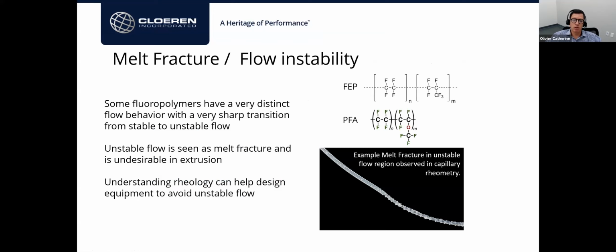For example, we designed a lot of dies for fluoropolymer applications. So here are some examples of fluoropolymers like FEP and PFA. So highly fluorinated molecular structures and very specific flow behavior. These materials tend to very quickly become unstable in the flow. And you can see here examples of the development of melt fracture in the strand that we collect out of the rheometer. As you can see, we are going from, in this case, a surface type melt fracture to a more volume like melt fracture.